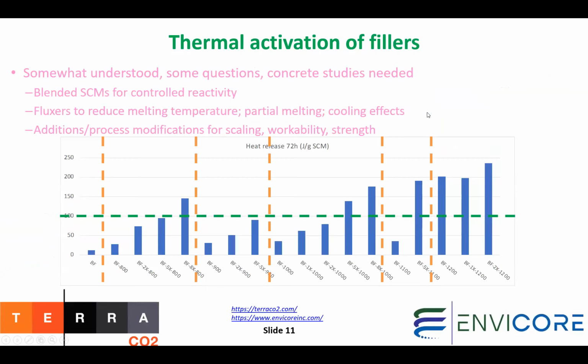So here is some studies from our group, which basically show that just for the basaltic fines itself, you have to heat it up to 1200 and cool it to get reactivity somewhere appropriate. But if you add about 5% to 8% of some material, which I won't tell you what it is, most of you can probably figure out what it is, what happens is we get the same reactivity, or at least more than threshold level reactivity, at 800 Celsius.